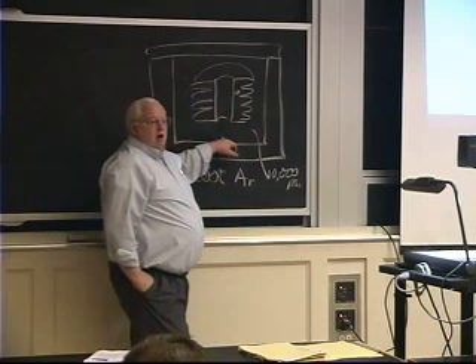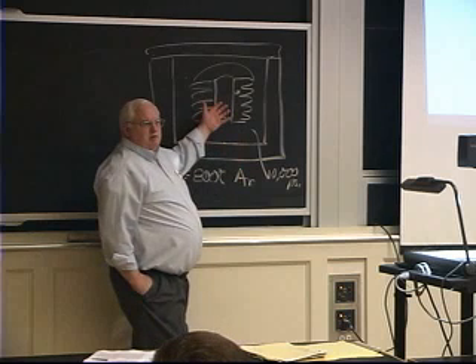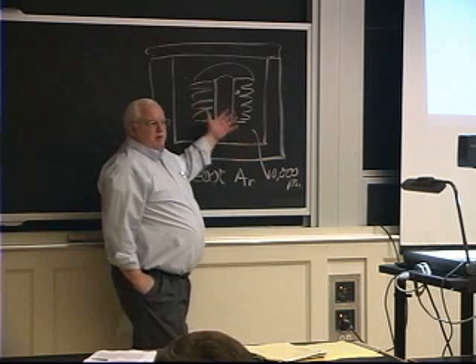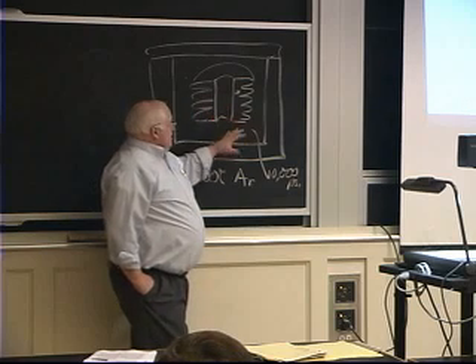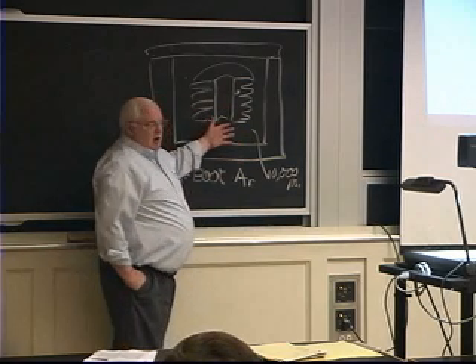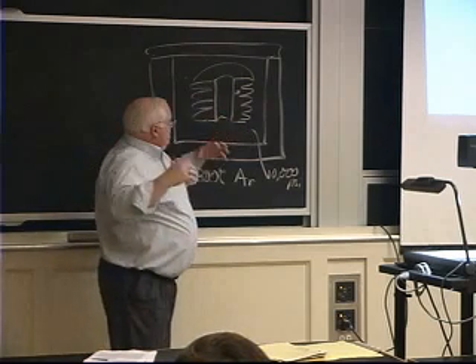So I'll heat this whole thing up to 800 degrees centigrade. In fact, what I'll do is I'll pressurize the argon at room temperature to about 3,000 psi, and then when I heat it up to 3 times the absolute temperature, okay, I get the extra pressure just by expansion of the gas, right? So I only have to have 3,000 psi argon pumps to get this thing hot and pressurize it. And what happens is that high pressure, this is called hot isostatic pressing.